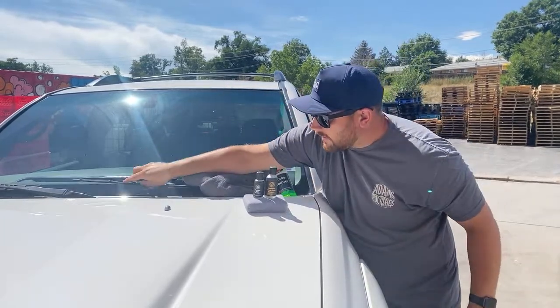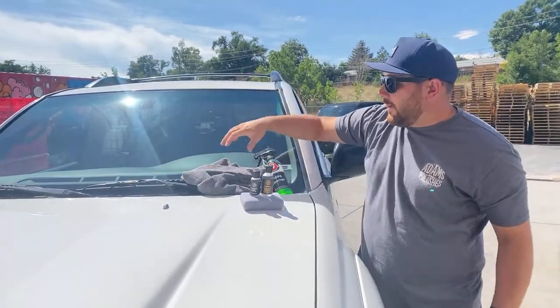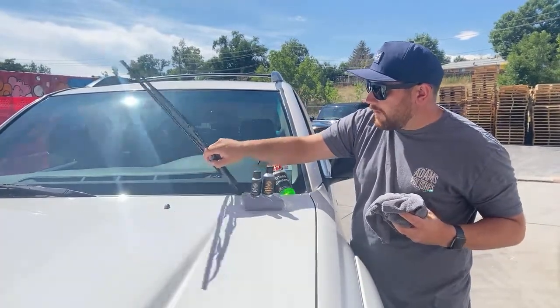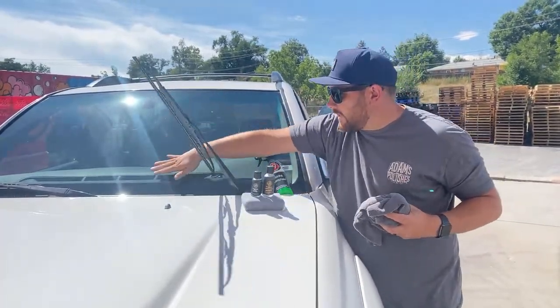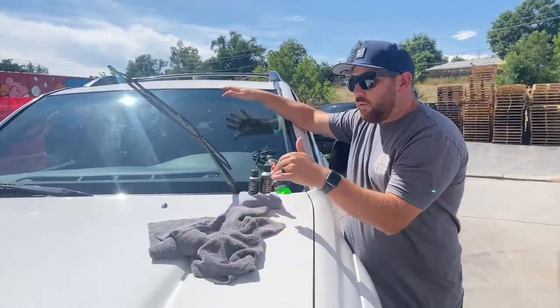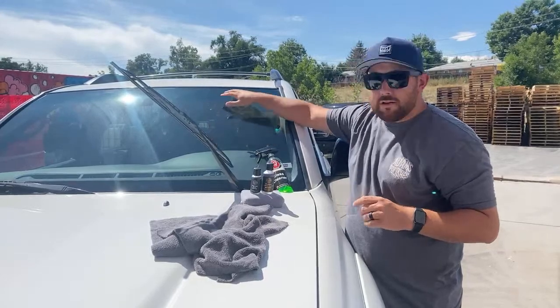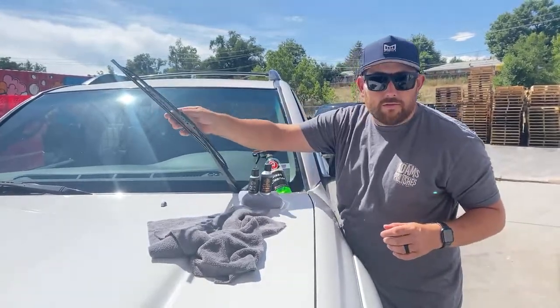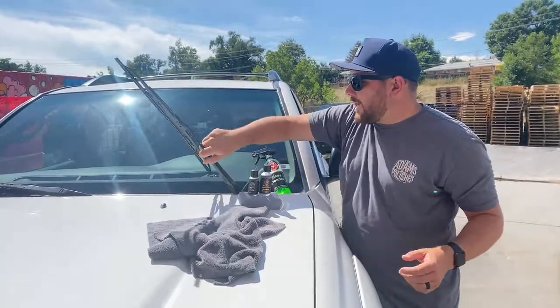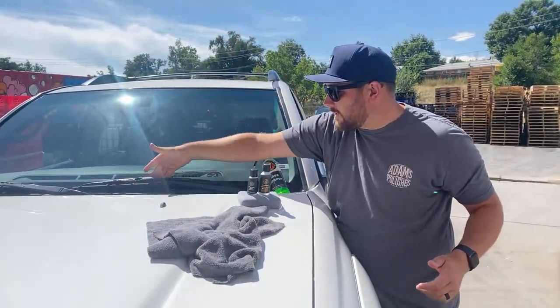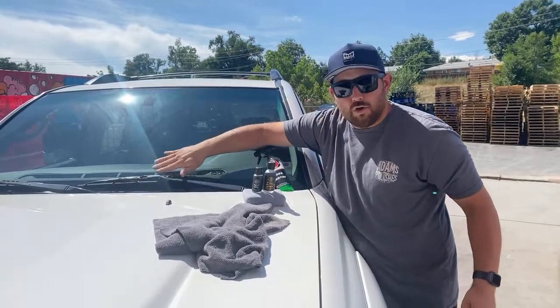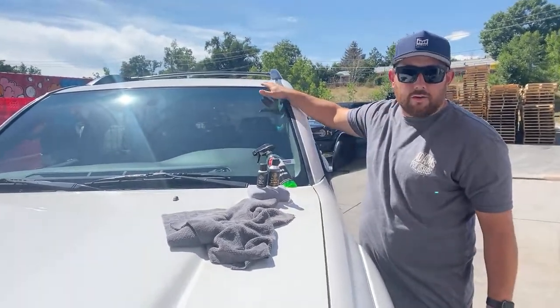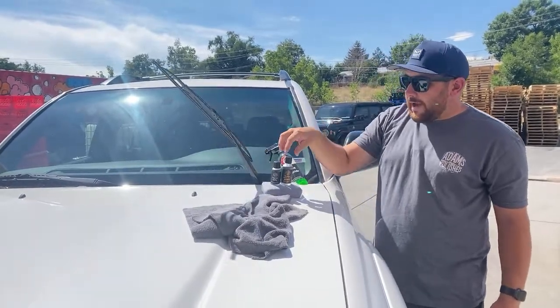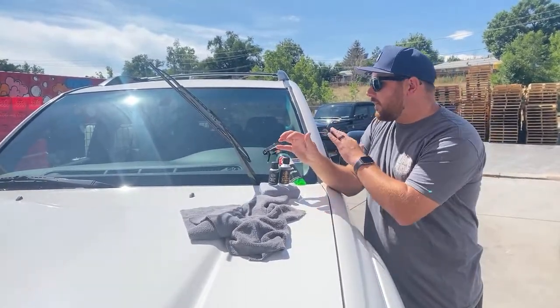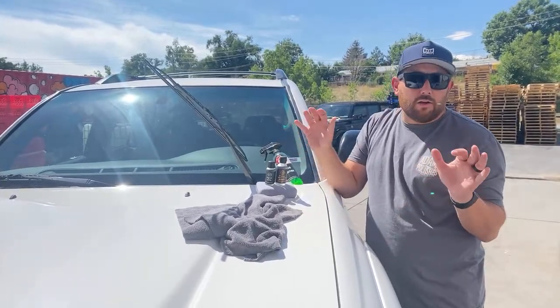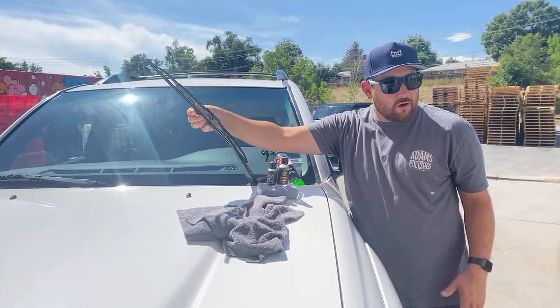And when these guys go, okay, your wiper blades, these rubber create friction as they go across the surface. Now, granted, with the graphene ceramic coating on there, it was a little bit more slick, but still, this rubber is very abrasive. And as these sit here, the dust and dirt sit and collect right here. So every time that these move, whoosh, they drag stuff on top of it. The only way to remove a graphene ceramic coating from either your paint, your glass, or anything, is abrasion. So these are abrading it away every time you run these.